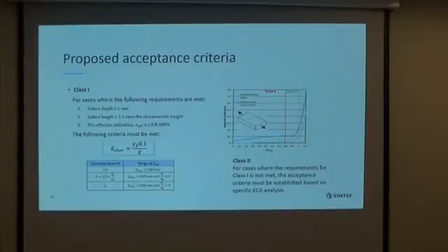And this is the first version of the proposed acceptance criterion from the first stage of our project. We have the typical crack driving force, the applied load, and the required CTOD value. We divide this curve into two classes, class 1 and 2. Class 1 is up to a utilization of 80% of yield stress, for cases where the following requirements are met: defect depth is smaller than 5 millimeter, defect length is smaller than 1.5 times the characteristic height, and the effective utilization is up to 80% of yield stress. If these requirements are met, we can use these criteria to design.